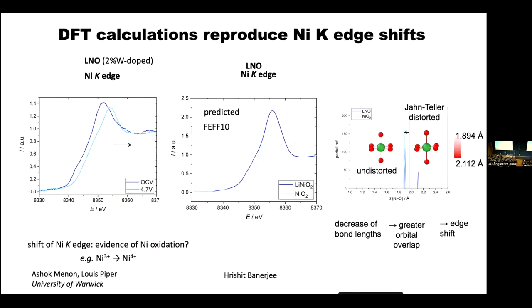And then people say, well, how do you account for these large shifts in the nickel K edge? This would normally be the signature of nickel involvement. But you can do DFT calculations and show that even with these types of mechanisms, the nickel still shifts. This is because you have very significant changes in the nickel-oxygen bond lengths because of this oxidation process. And that causes the edge shifts in the XANES.